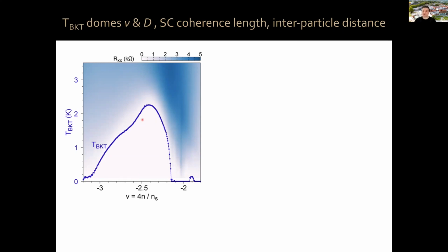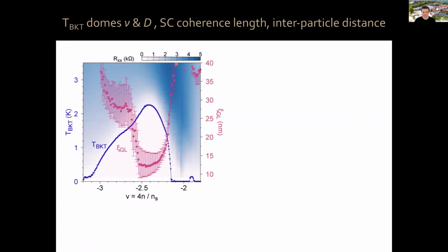Now, very interestingly, by doing temperature-dependent measurements and magnetic field measurements of the system, we can extract the superconducting coherence length, the Ginzburg-Landau superconducting coherence length, as a function of filling at this optimal electric field, okay? And this is what it looks like. The superconducting coherence length decreases, it sort of bottoms around optimal doping, and then has a jump up and then continues evolving, okay? This is an extremely short superconducting coherence length for this ultra low density superconductor, okay? Just to give you an idea of this, let me plot the average interparticle distance for the system along the same axis. So you can see that the superconducting coherence length is pretty much bounded here by your average interparticle distance.